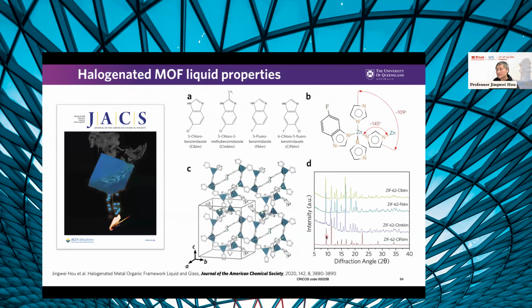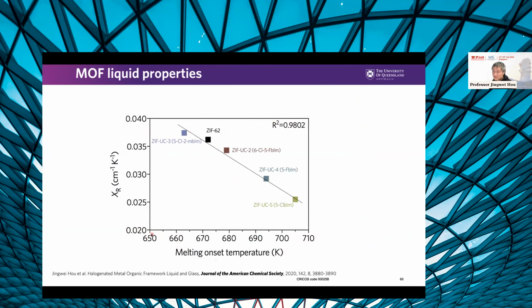The other thing is, as I mentioned at that time, we only have access to a small number of MOFs that can be melted. So how can we functionalize the MOF, and how can we understand the melting mechanism of the MOF? Simply by functionalizing the MOF structure itself. Thanks to coordination chemistry, we can use different functionalized ligands to functionalize the MOF glass, as the crystal material does. By putting one atom onto the benzimidazole ligand, we managed to make the halogenated MOF liquid and halogenated MOF glass. You may think, only one atom, that doesn't look too different, but we were surprised to see how much difference it can make in terms of melting temperature. Even though it's only one tiny difference, the melting temperature difference spans over 50 Kelvin for different materials.